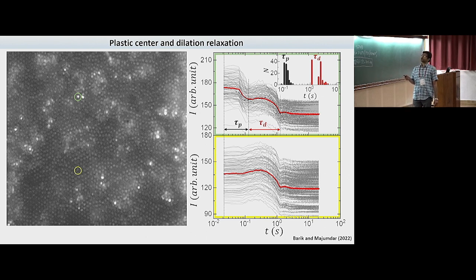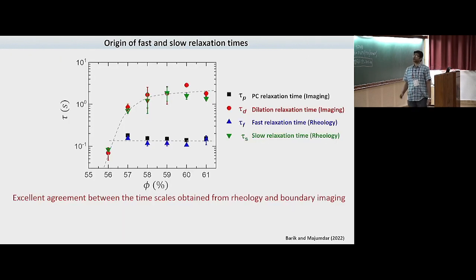So where we got a two-step relaxation, we considered hundreds of such spots. You can see that there is a two-step relaxation, and from here we define two time scales. This plastic center relaxation time, that is the first step, and after that, once these spots disappear, that is the dilation relaxation time scale. If we take another region which doesn't have a plastic center, it just shows a single step basically.